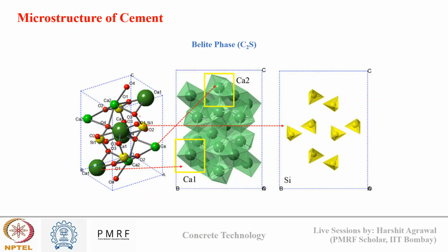While if you see the image of C2S, each silica tetrahedra is only surrounded by two calcium ions, which is sufficient to satisfy the charges. You can see this is the silica tetrahedra, these are oxygen bonds of that silicate, and you can see there is calcium which is bonding towards 2 oxygens of each tetrahedra. So compared to C3S, this arrangement leads to better packing efficiency because all bonds are clearly defined in C2S. And that's why C2S forms at lower temperature rather than higher temperature, because it has a more stable structure compared to C3S. And that's why it is less reactive also. The more stable the structure is, the less reactive it will be.